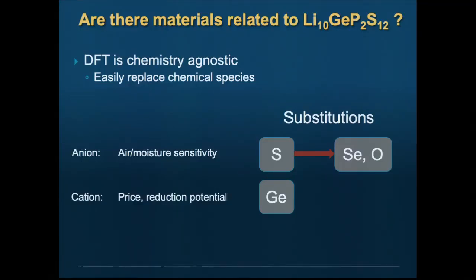To us, this was a proof of concept, so we right away started figuring out, can we replace sulfur? Sulfur's not great, right? If you expose sulfides to air, they make H2S, which is not a pleasant thing to work with. People are really worried about that in factories, because you can control it until something goes wrong. You get moisture infiltration in your process, and suddenly you have to evacuate the factory because you have toxic gases going around. This is actually not so much a problem in the battery. This is really a production problem.